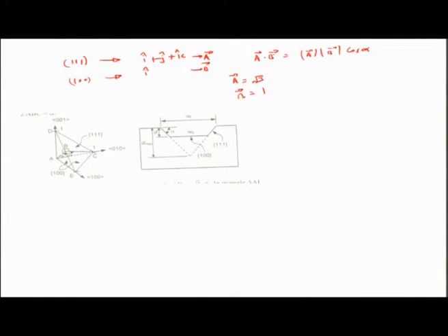So we are left with A dot B, which is actually equal to i dot i, 1, and 0 dot j and 0 dot k, which are all eliminated, being equal to the mod of A, which is root 3, times the mod of B times cos of alpha. So alpha really is the arc cos of 1 over root 3, and this happens to be around 54.74 degrees if we calculate cos inverse or arc cos of 1 over root 3.